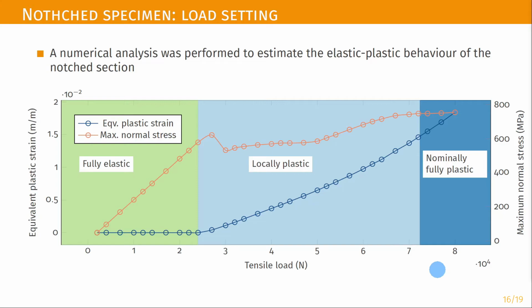This is in order to achieve the different behavior observed between torsion and bending that we saw before in the welded joint. From this graph, it can be seen how the equivalent plastic strain and the maximum normal stress vary as the preload changes. So we can in fact identify three main regions. The first one where the material remains in an elastic regime, the second one where there is a localized plasticity around the notch, and the last one where we have a nominal generalized plasticity in the notch region. In the following, I will present the first experimental results for pure torsion with a static preload of 10 kN, thus keeping the specimen in the elastic region.